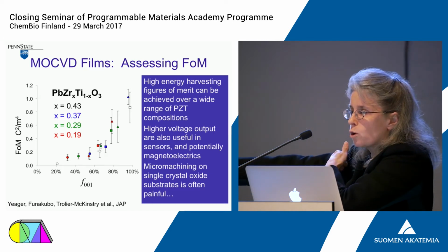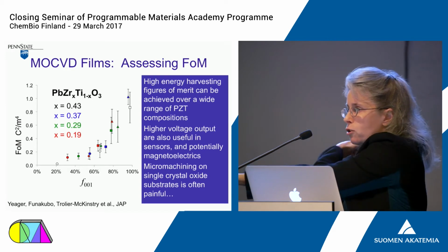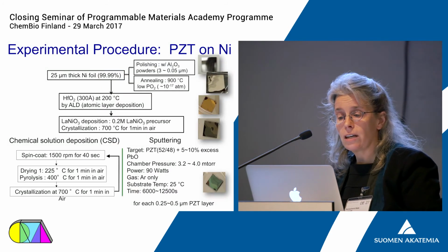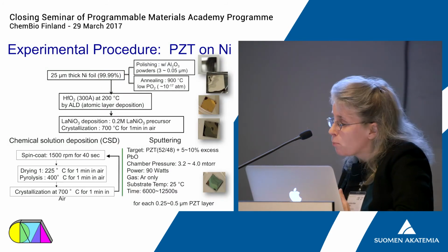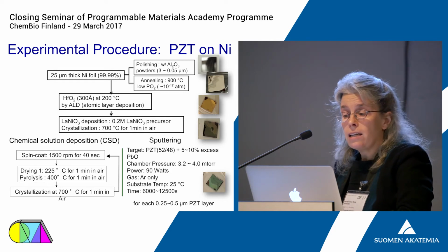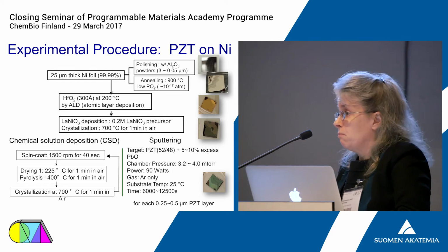And so our devices work once, and then a crack runs through the root of the cantilever and destroys the device. Well, this was very depressing, so we decided we were tired of this, and we thought perhaps we should work on a material that's inherently more mechanically robust. And metals, of course, are really quite mechanically robust.